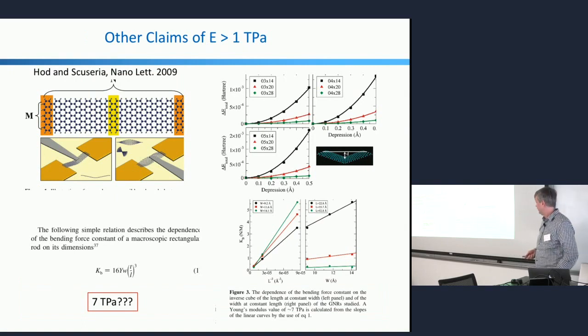This is a little older, from 2009. This was again a molecular dynamics simulation of bending of a nanoribbon. The basic idea is that in your MD simulation you make a 5 nanometer long little thing and you bend it with a 0.5 nanometer indenter, which I wish I had, but you can do anything in MD, right? And you see some kind of cubic behavior and you say, hey, this is like a beam bending, right? And I can look up the formula. There we are again. Look up the formula for beam bending and it has Young's modulus in it, right? And you see something varying as the inverse cube of the length. And you say, aha, it must be this formula. And they get 7 terapascals.